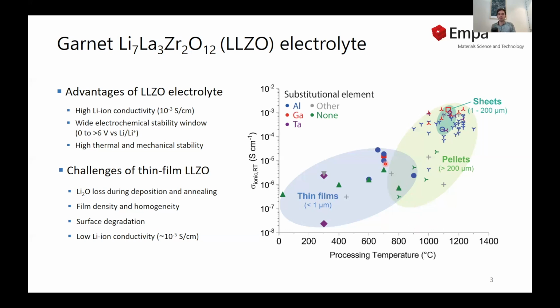from 1 to 2 orders of magnitude lower. The challenges of thin film LLZO processing are the high surface to volume ratio that leads to massive lithium losses during the deposition and sintering step. This forces one to lower the processing temperature, and of course, this has an impact on the density and homogeneity of the films. Also, higher surface to volume ratios make these films much more sensitive to air or any kind of surface degradation. Overall, this has a significant impact on the ionic conductivity, with maximum values achieved in the 10 to the minus 5 siemens per centimeter range.